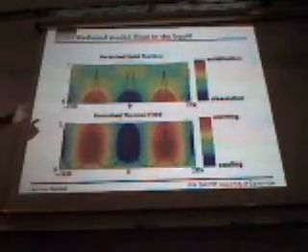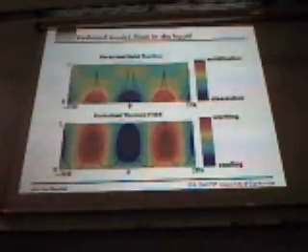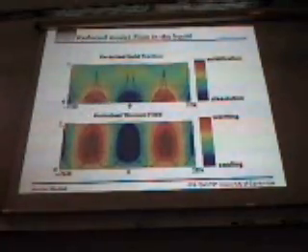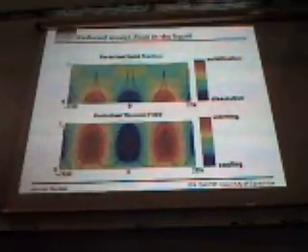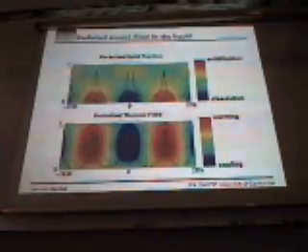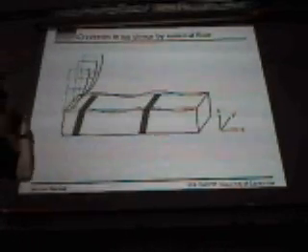When you have this flow going over this corrugated ice liquid interface, you have streamlines where upwellings correspond to the peaks and downwellings correspond to the troughs, and this leads to cooling underneath the peaks and warming underneath the troughs. But more importantly, this leads to dissolution of the matrix. And so you're changing the phase fraction again by forcing flow within this mushy layer, the ultimate fate of which is likely to give rise to these regions of zero solid fraction. Here, of course, you've broken the symmetry by applying a shear flow from left to right. So instead of these point regions of zero solid fraction, which we saw in the buoyant convection, you get these planes of zero solid fraction aligned perpendicular to the external shear flow.